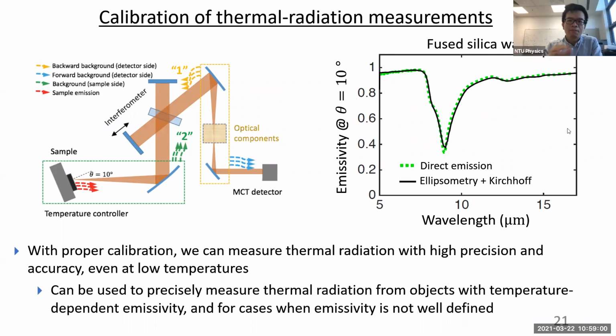Yeah, that's right. So we did a benchmarking test. This is the emissivity that we measure using this direct emission measurement from a reference sample, which is just a flat polished wafer of fused silica, and that's the green curve over here. And this is emissivity at an angle of 10 degrees, but unpolarized. And then the black line that's laying on top of it is ellipsometry data.